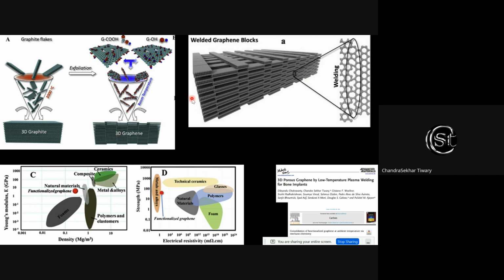Apart from that, we can easily weld this graphene structure by spark plasma sintering, where the interface gets welded. Now, this kind of welded, solid structure of graphene, which is very similar to graphite, does have porosity of around 50%. Still, it has strength almost like some of the solid materials, and the density is way lower. So if you see this Ashby map, which is utilized to see material performance in structural applications, the modulus versus density map is generally utilized. So what we do here, these are the foams, polymers, metals, and so on.